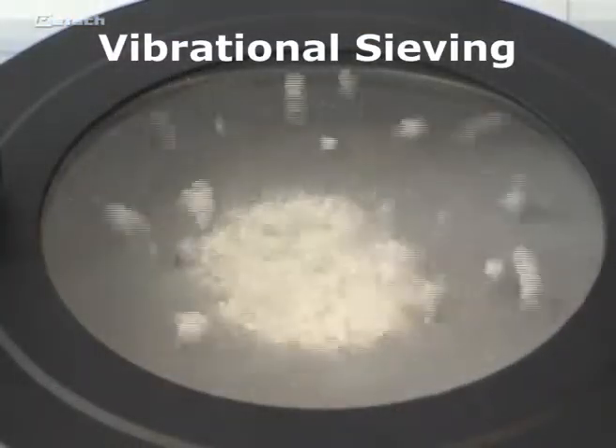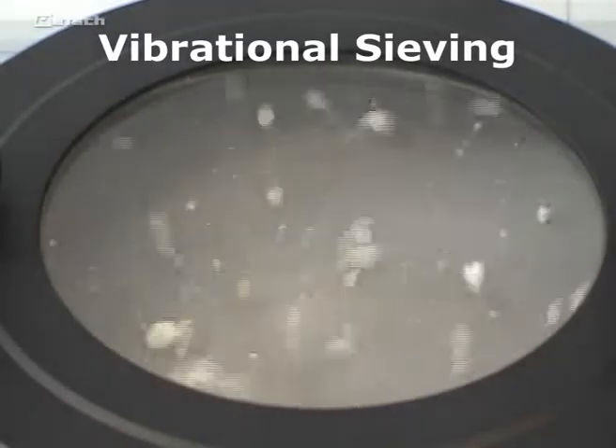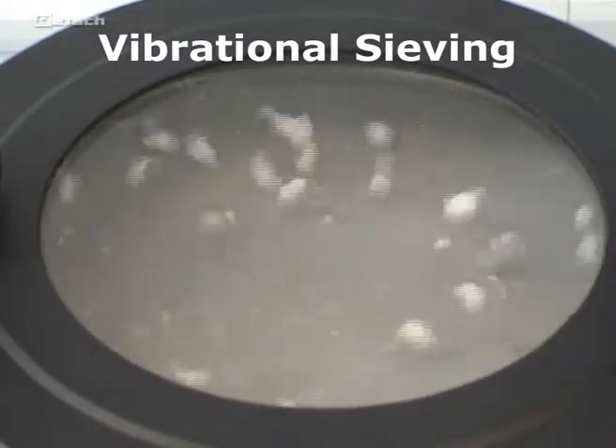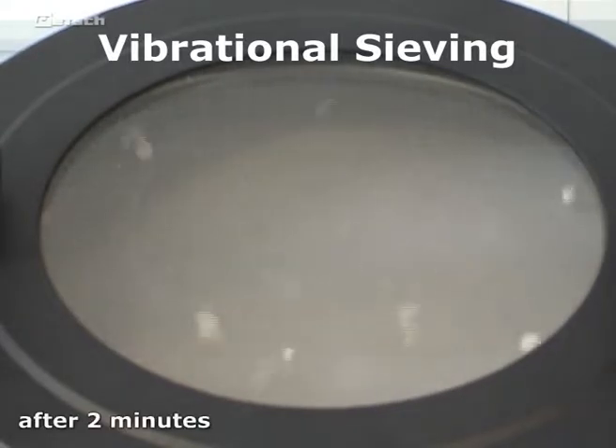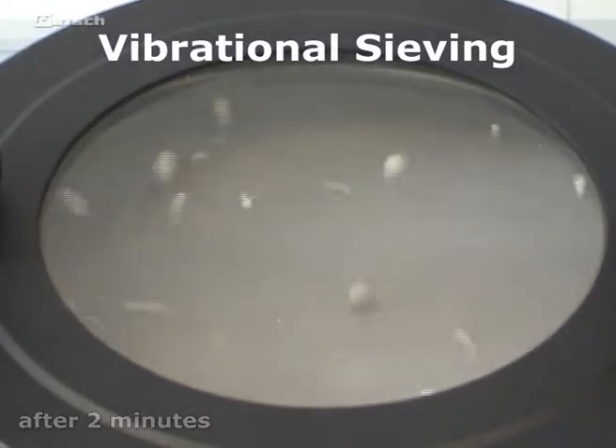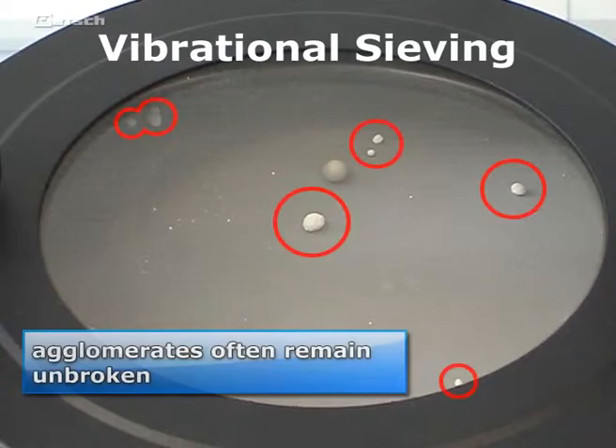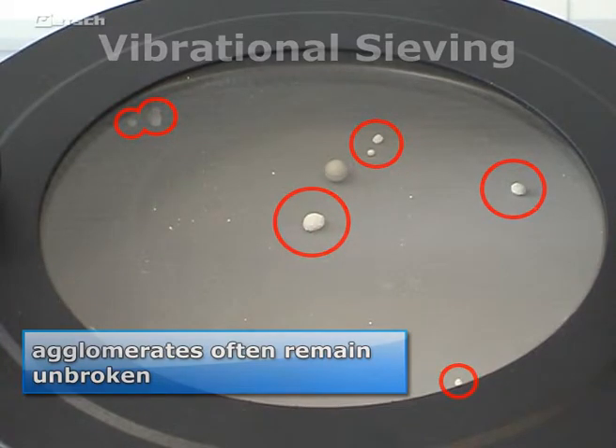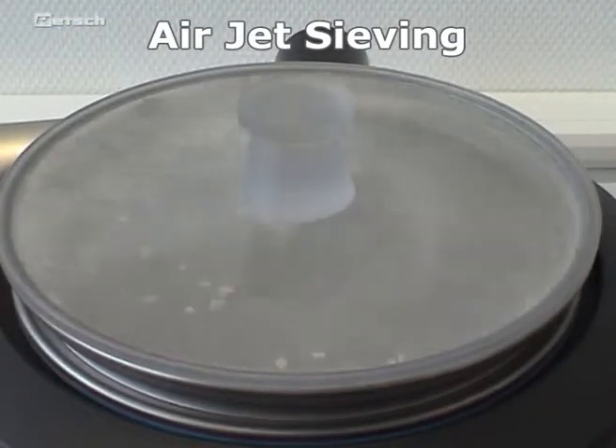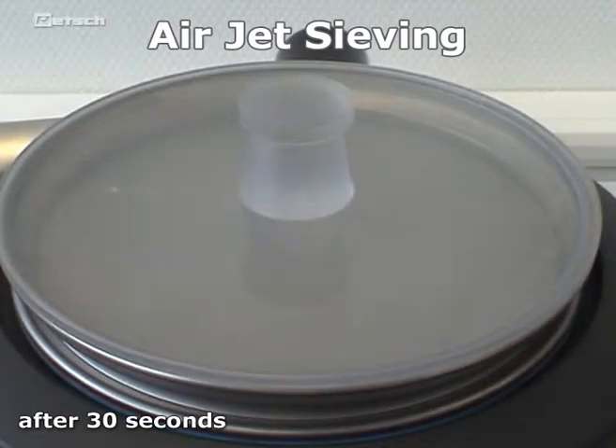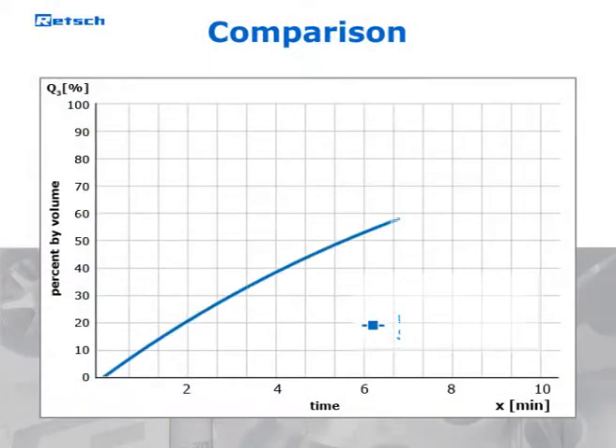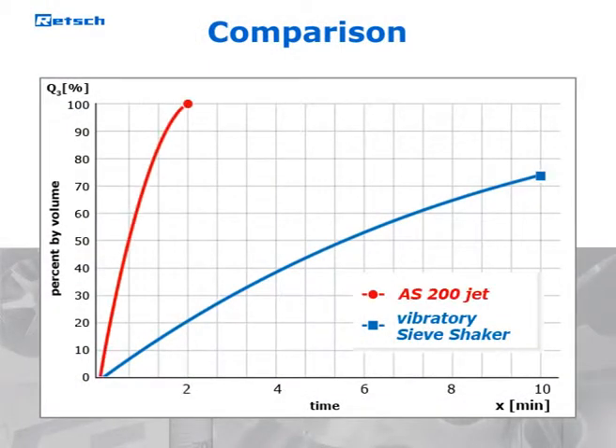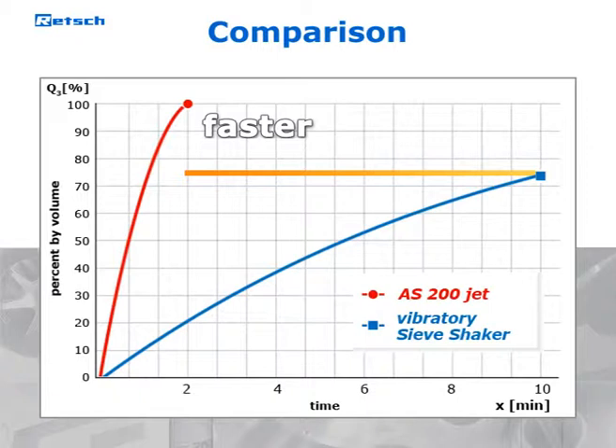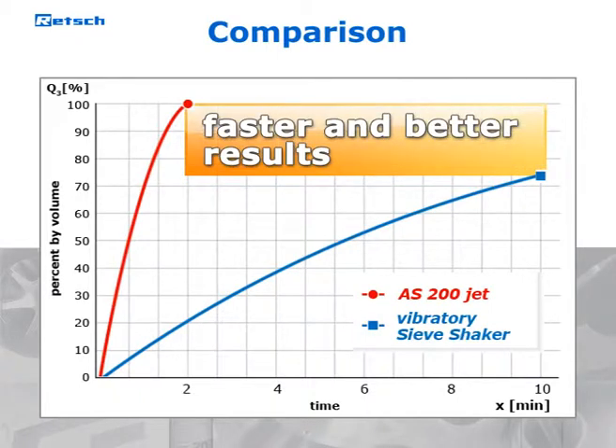Vibrational sieving of sensitive or very light sample materials with a tendency to agglomerate, which primarily applies to particles smaller than 200 microns, is very difficult. It is definitely problematic for particle sizes below 63 microns. In this size range, air-jet sieving is the perfect solution. Compared to vibratory sieve shakers, the AS200 Jet provides for fine materials sieving results with a higher degree of separation efficiency in only a fraction of the time.